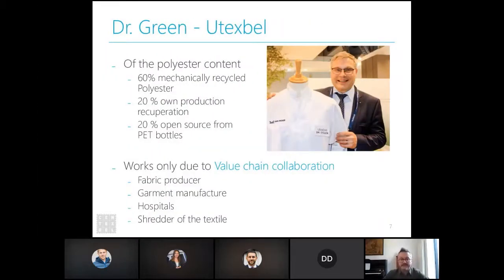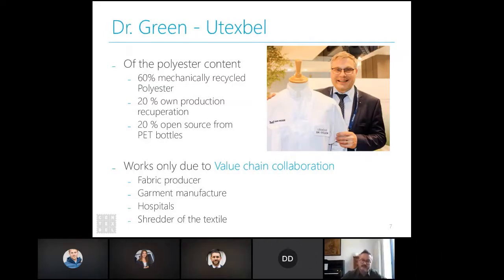A company that was very successful within this technique is Utexbel. They bring into the market, together with garment manufacturers, garments for hospitals, for medical caretakers, that consist of about 60% polyester and then cellulosic fibers, polyester or cotton. And from that 60% polyester fibers, 60% is mechanically recycled. But you see that to maintain a certain quality, they still need fibers from another source, like open source PET bottles. So they come from outside the textile industry. That's why we say open source.